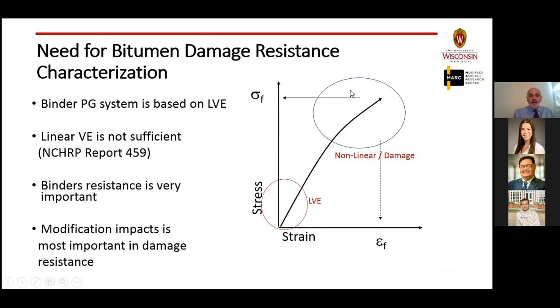Is this a new concept? The answer is no. NCHRP Report 459 was published about 20 years ago. It was very clear at that time that when they tested modified asphalts in particular, they found that there is really a disconnect. And I'll show some of the data from that old report. What we found is that binder resistance to damage is extremely important. Therefore, if you want to characterize and select these binders, you better be in that range.